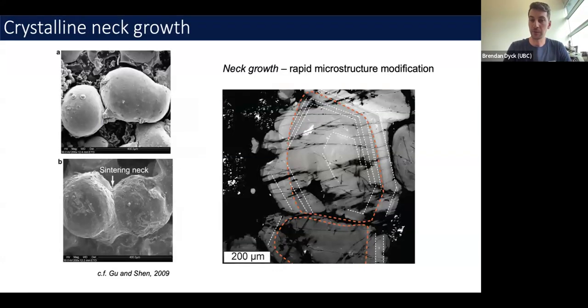Now, another thing we can look at with this sintering, if we think back to those two gold particles coming together: immediately after they touched, they tried to maximize the area of that grain boundary that was low energy. And they do that by reorganizing or reshaping some of the higher energy part of their grain boundary, which in the case of the gold is the portion of those nanoparticles that wasn't touching along that grain contact.